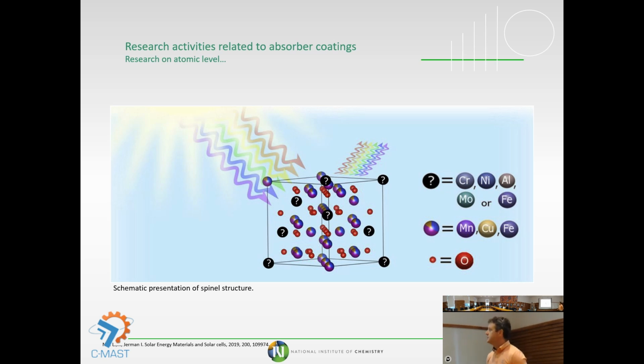So we studied the spinel structure, where those black pigments are normally stable up to 1000 degrees or even more. Those pigments are quite often also used in car glass. On the top of the car there is a black shade to protect your view. So similar pigments are used here. They are composed of manganese, copper, and iron mixed oxide, and we tested different additions. We add different elements in order to change the structure, to incorporate them somewhere in the spinel structure and to tune the optical properties.